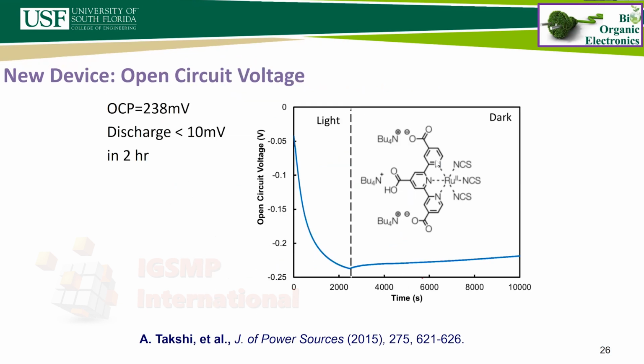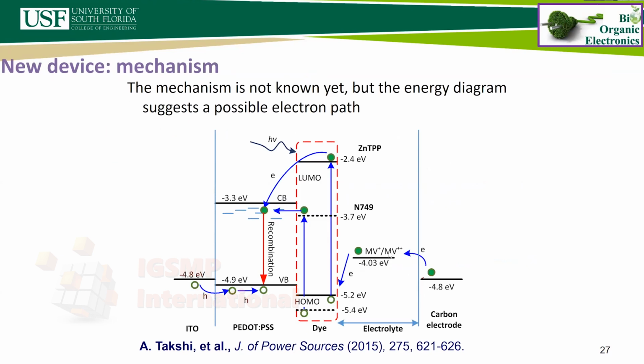And even changing to a different dye, we were able to get a much more stable voltage after we stopped shining the light on the cell, meaning that the device had a much lower recombination rate, and the charge storage stability was improved. So we looked at the mechanism, and it's all about, as we heard very briefly, the HOMO-LUMO structure of the material. So we are taking advantage of that for energy harvesting and storage.